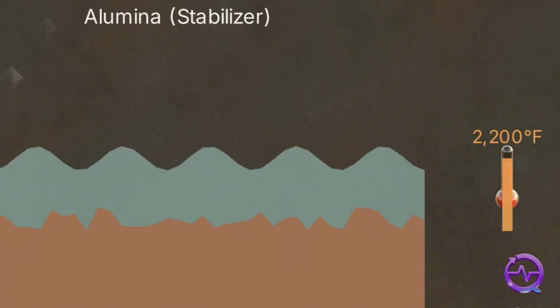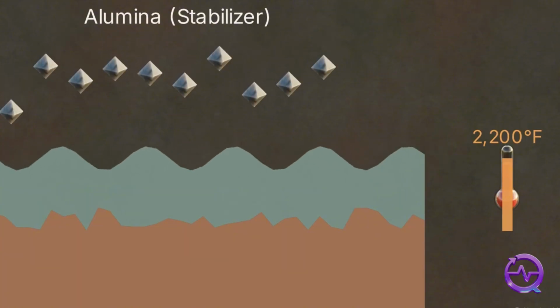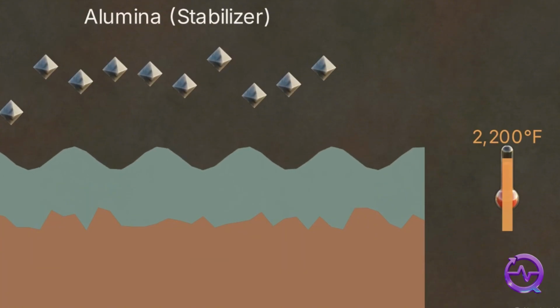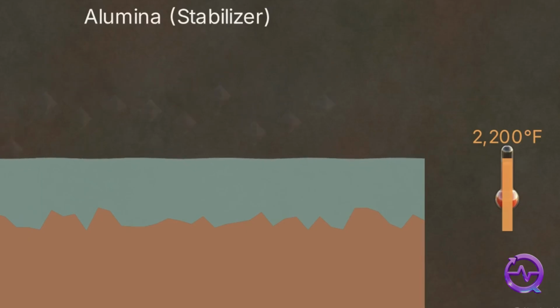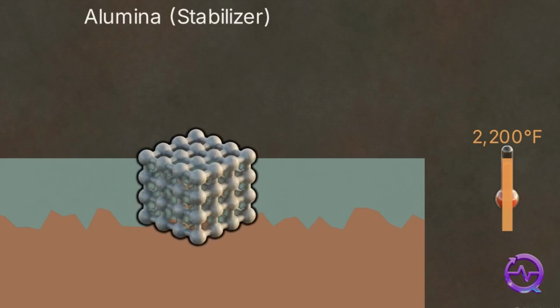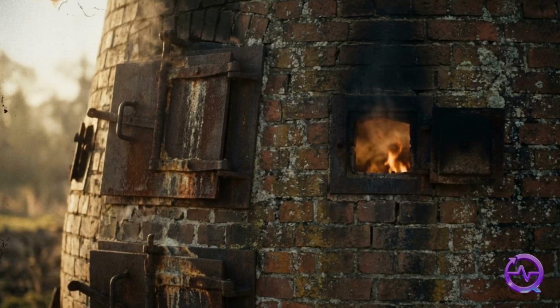They chemically intervene to lower the melting point of the silica, allowing it to flow and form a smooth surface at lower temperatures. Finally, stabilizers like alumina are added. Alumina increases the viscosity of the melt, which prevents the molten glass from running off the pot and ensures a durable, even coating. Beyond the ingredients, potters can manipulate the kiln's atmosphere.